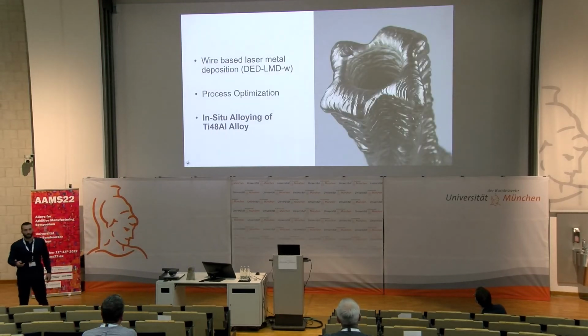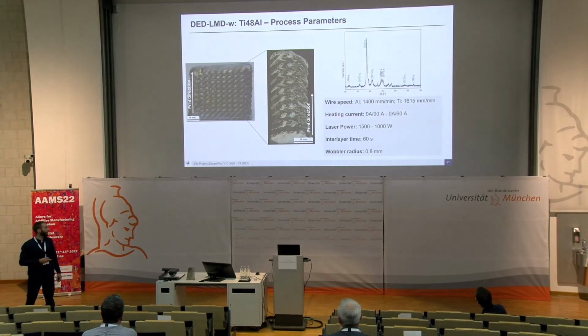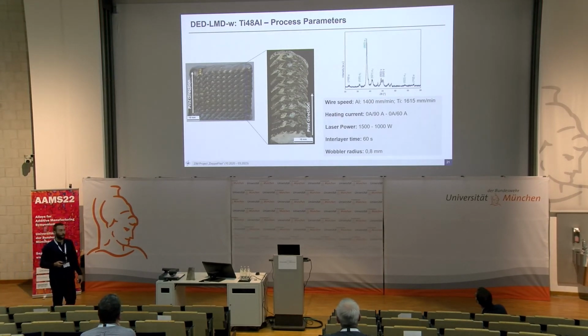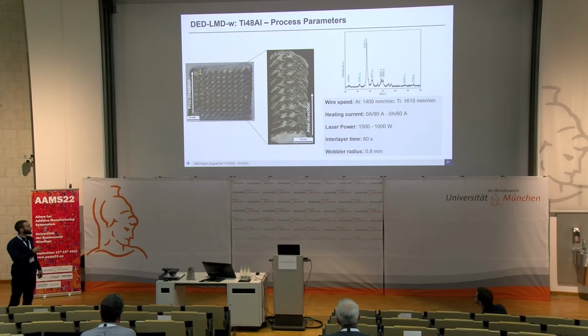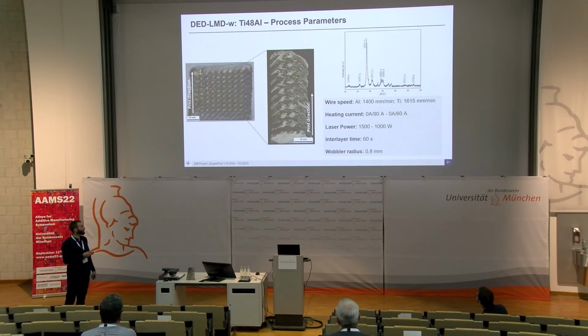Now we're going to talk about the in situ alloying of the alloy we're speaking about. I have to say, all the experiments we did here are without a heatable building plate. On the left we see the cube, and here the microstructure. It's pretty inhomogeneous, as we see. And here, for the people who like numbers, we have the process parameters. What's interesting to mention is that we work with an interlayer time of 60 seconds to control the cooling.